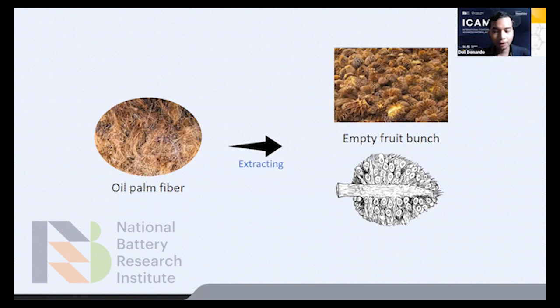Fibers have a porous surface morphology, so they are very useful in improving mechanical properties when joined with a polymer matrix because of their mechanical interlocking ability. Furthermore, OPF or oil palm fiber has a relatively low density of 0.7 to 0.9 gram per centimeter cubed, tensile strength of 50 to 400 megapascal, and Young's modulus of 0.57 to 9 gigapascal.